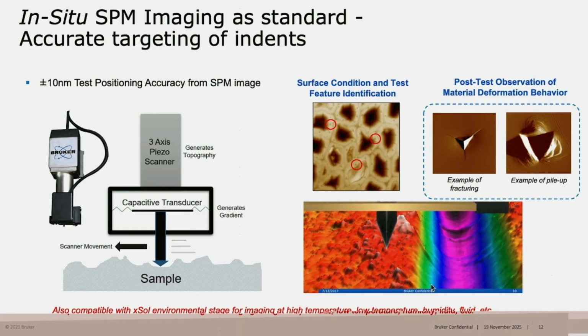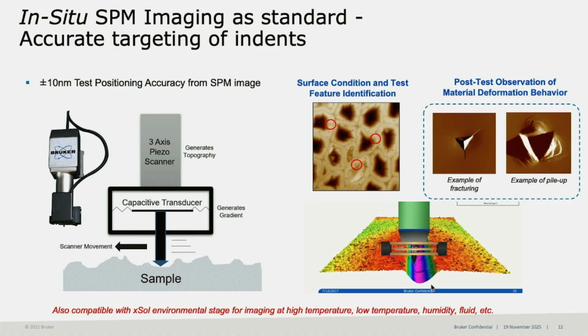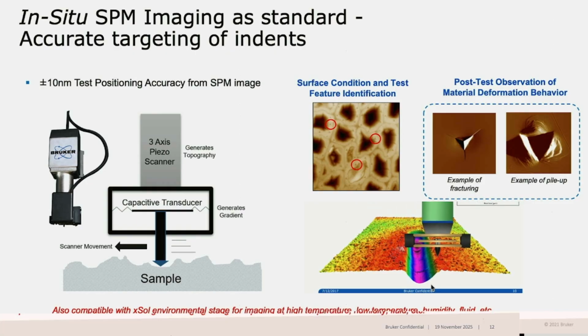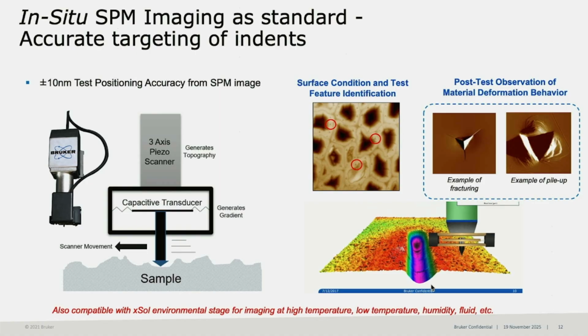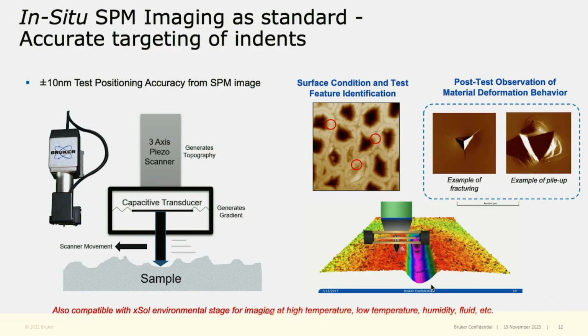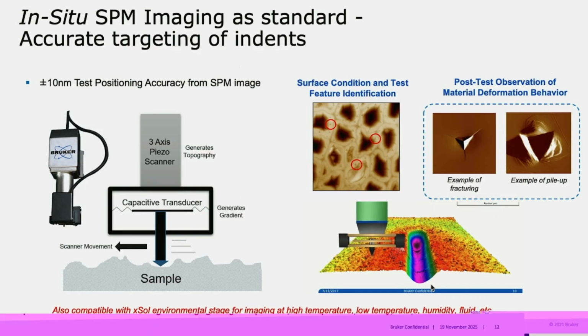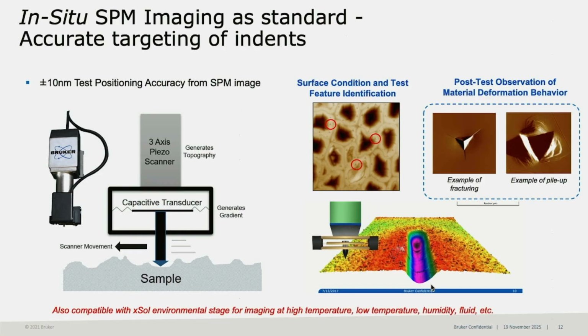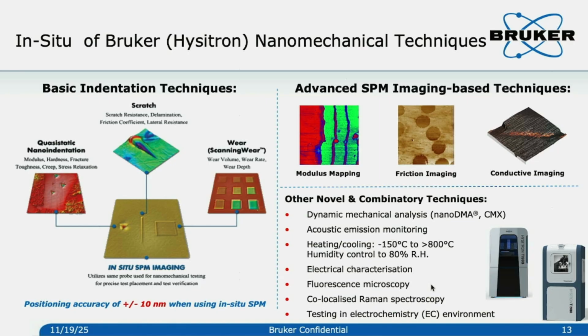Then you can calculate the fracture toughness. This is very useful for the hard coating, thin film, right? And this is also useful to measure some mechanical properties on metal, on alloy. You can see from the, we call the amorphous material, you can see we call the pile up of the material after the indentation, right? This is about the in situ scanning technology.